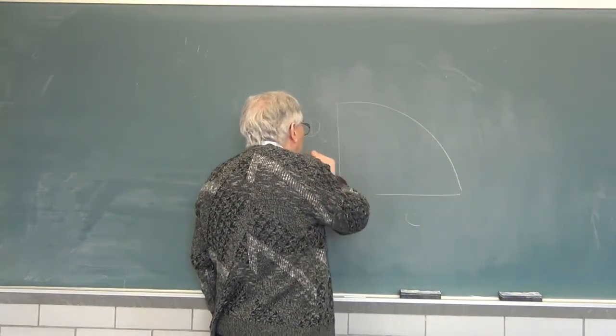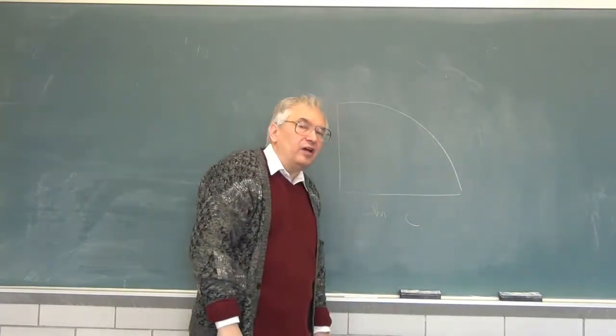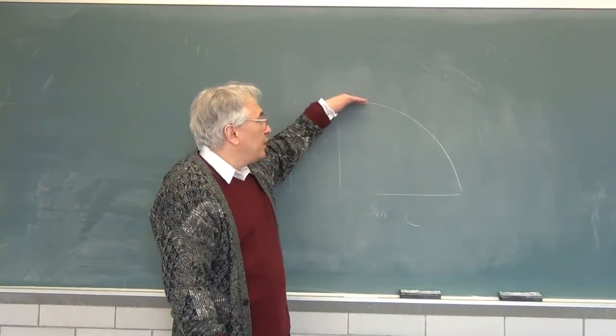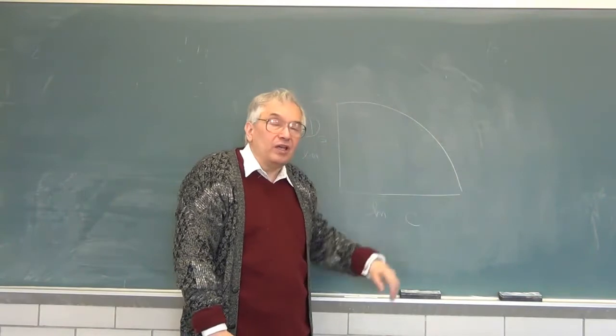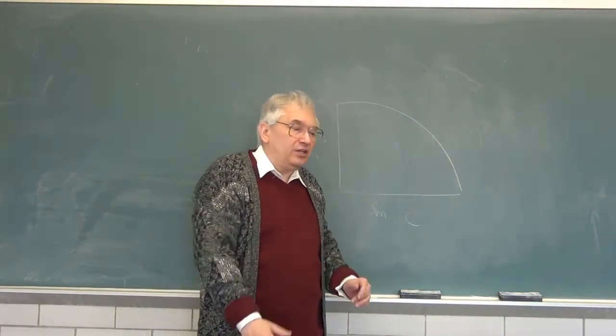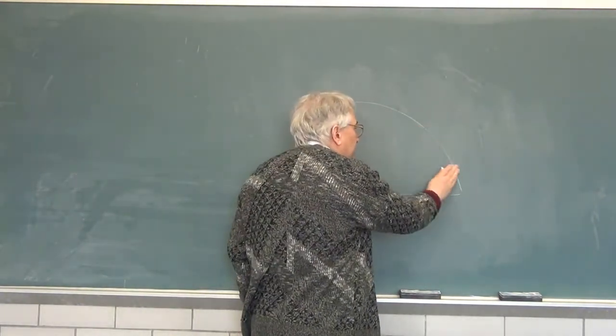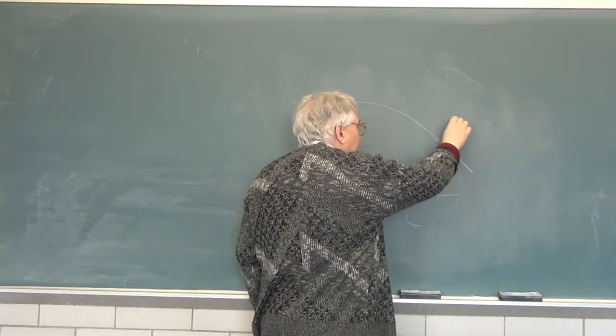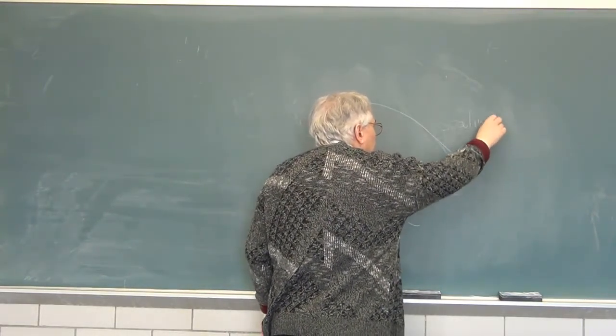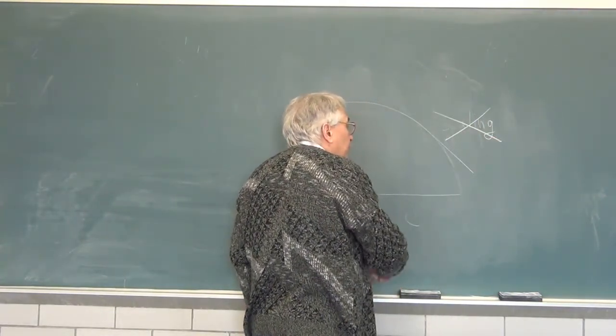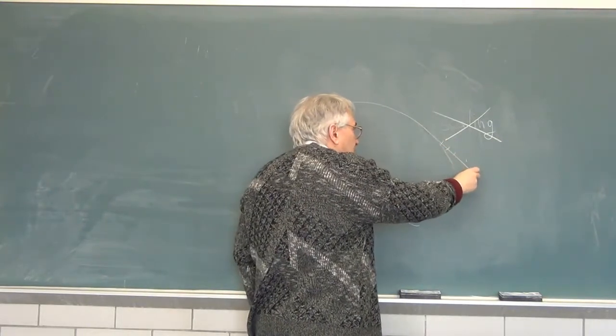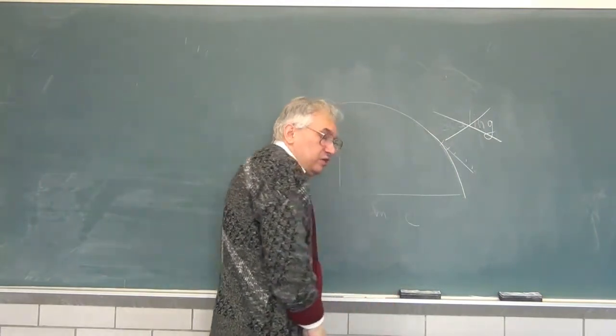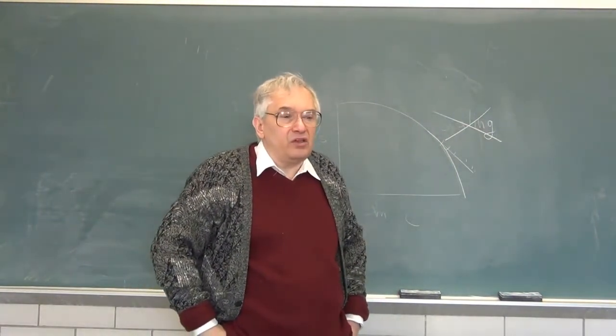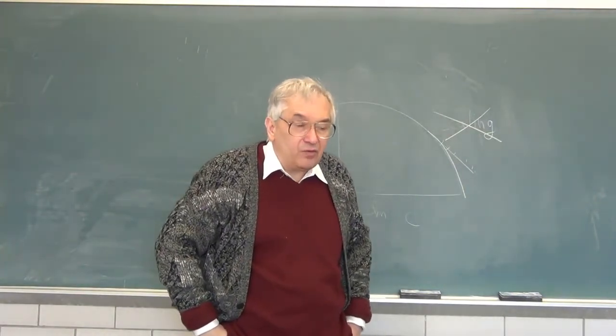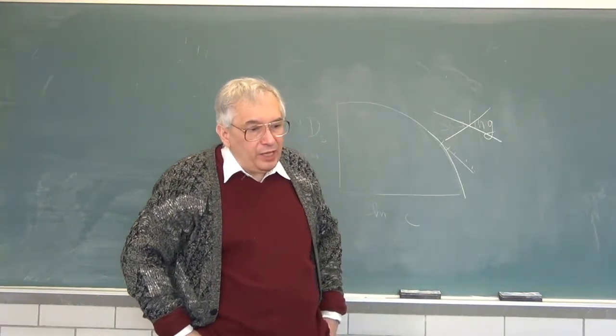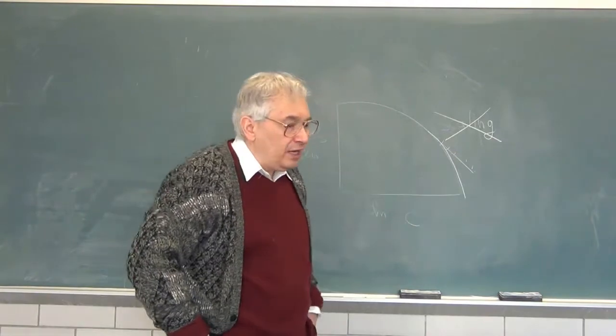You see a smooth curve of constantly increasing slope on a log-log plot. We start out quite close to flat, we roll over, we go downhill. There is absolutely no indication in the measurements of a well-defined region in which you see a transition to scaling behavior. That is, if you look at the Lodge measurements and ask where is scaling, it's quite clear that there isn't any. There's no region on a log-log plot where you see a straight line. Instead, you see a smooth curve of constantly increasing slope. And that smooth curve of constantly increasing slope is the extremely uniform behavior you find for polymer self-diffusion. Well, we can push ahead, and we can also look at figure 8-20.